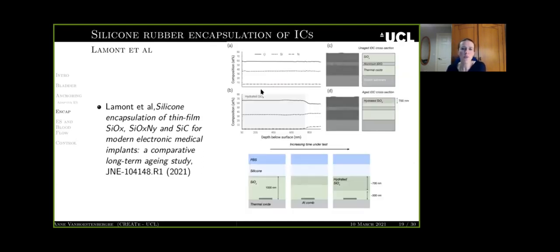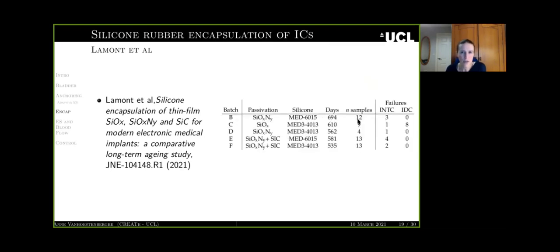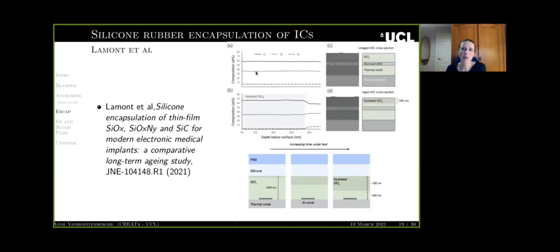So just very briefly, what he observed in batch C, the batch that failed, the only one where we can try to understand what causes failure. Probably the failure mechanism in this batch would be similar to the failure mechanism in the others, but they may just be much slower. And what he observed was a hydration effect. You can barely see it on these 2 images, but as you dig through the different layers, where the top of the IC is here, what you're going to observe at about 600 to 700 nanometers is a change in the composition that indicates that the top layer had become hydrated over time.